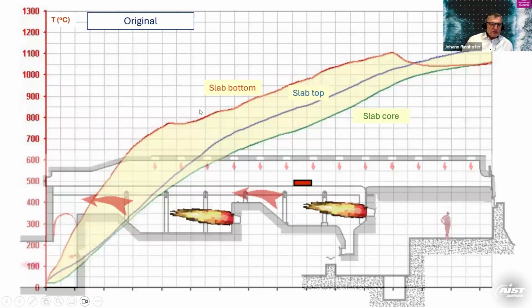Originally, the furnace looked like that. So we had, as I said, very large burners here in the lower furnace. That means the slab bottom temperature went up and went up. It was very high temperature, a lot of scaling there. In the end, very high temperature differences in the stock, all sorts of things you don't want to have. And that was necessary in order to arrive here before we go into the soaking zone at a very high temperature, because we have no option to heat from the bottom in the soaking zone here.